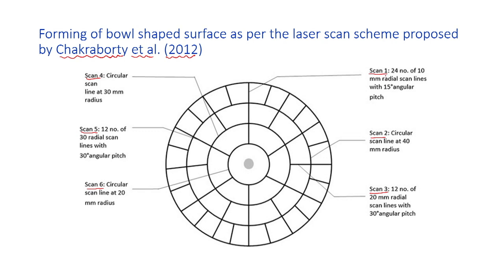So, the scan pattern number 1 is suggesting to have 24 irradiations, and this irradiation length is around 10 mm, and these irradiations are radial scan lines with 15 degree angular pitch. So, 10 mm radial lines with 24 irradiations to be applied, that is scan 1. After that, scan 2 is having a circular scan line, and that circular scan line is of 40 mm radius. So, that is this 40 mm radius circular scan line.